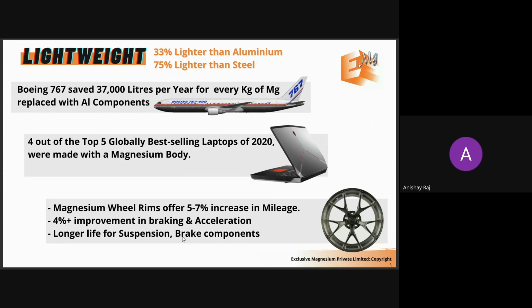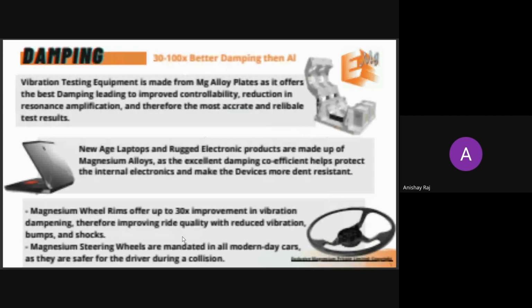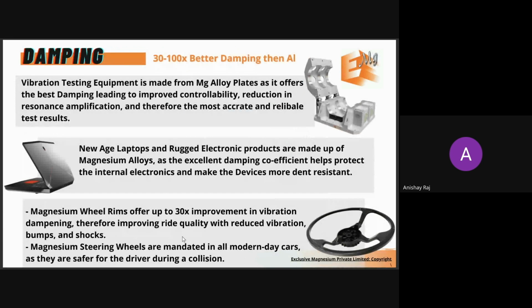So in terms of mileage, just by replacing an aluminium wheel rim with a magnesium wheel rim, you'll get a 5 to 7% increase in mileage, right? And you get a 4% improvement in braking and acceleration. You'll get longer life of suspensions and brake components. So that's one. The second major one is damping.